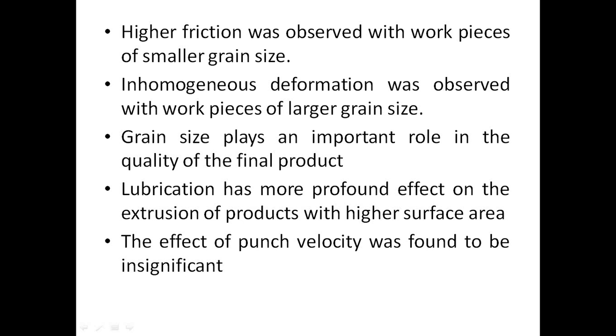Higher friction was observed with workpieces of smaller grain size. Inhomogeneous deformation was observed with workpieces of larger grain size. Grain size plays an important role in the quality of the final product. Lubrication has a more profound effect on the extrusion of products with higher surface area. The effect of punch velocity was found to be insignificant.